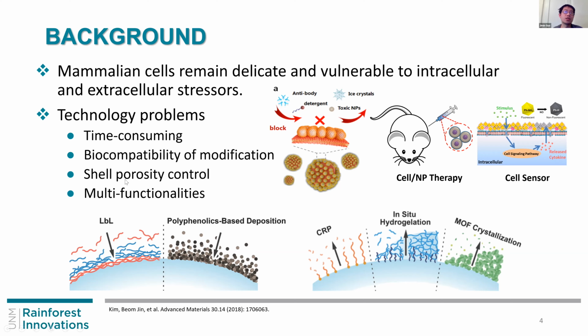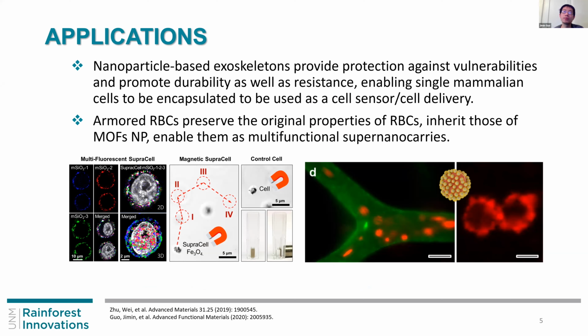We can also control the shell properties because the nanoparticle is already synthesized. So the nanoparticle pore size is already designed, so we know the porosity. But for all the rest, it is typically out of control, just to make sure they can coat on the surface. Also, we can choose different nanoparticles. I will show we can have multi-particle coating on the same cells, which indicates we can do multifunctionalization, what we call armored cells or supercells, something like that. So the application, as I said, is first that they can provide protection from the stress.